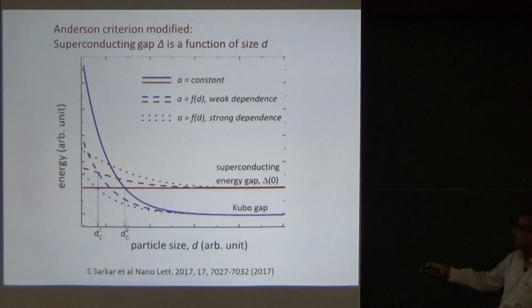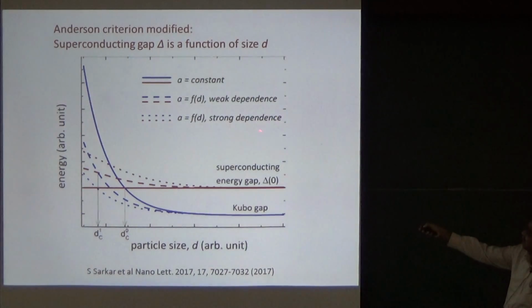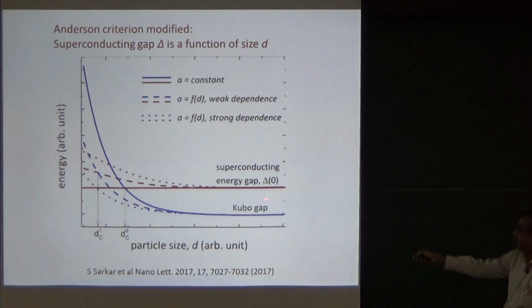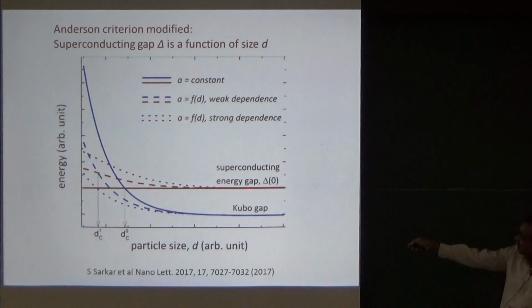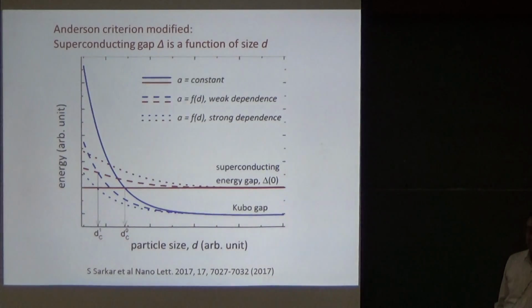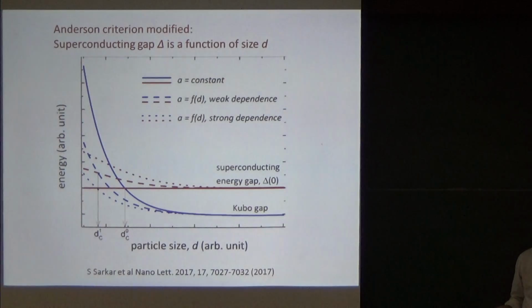But now we find that because there is expansion of the lattice, if there's a weak dependence of the lattice constant on the size of the nanoparticle, you will just prolong the crossing at which the Anderson criterion occurs. But if you have an even stronger dependence of the lattice constant on particle size, you will basically have superconductivity even at lower sizes. Okay, so that's the explanation that we have for the existence of superconductivity well below the Anderson limit on the size.